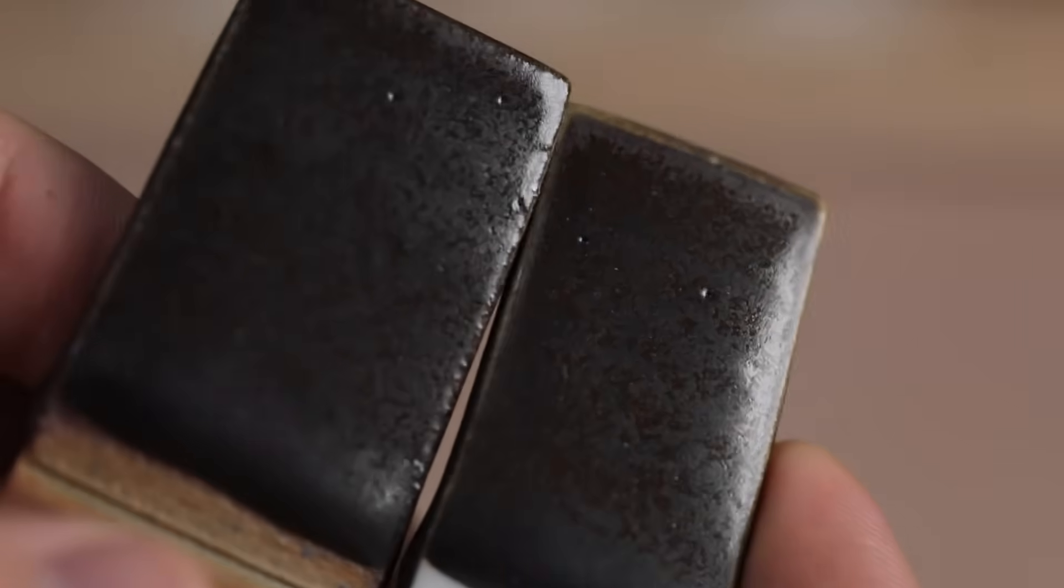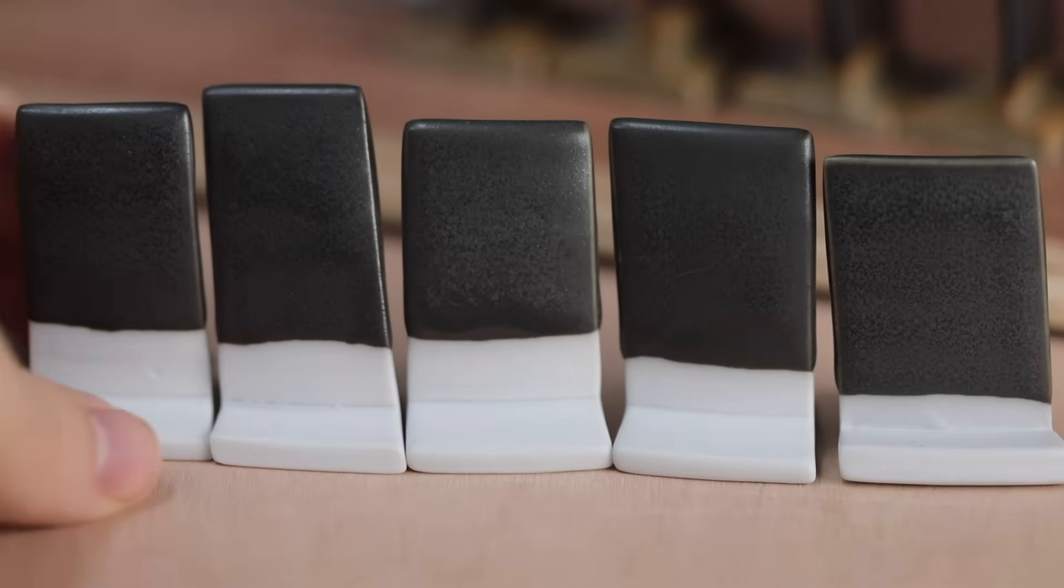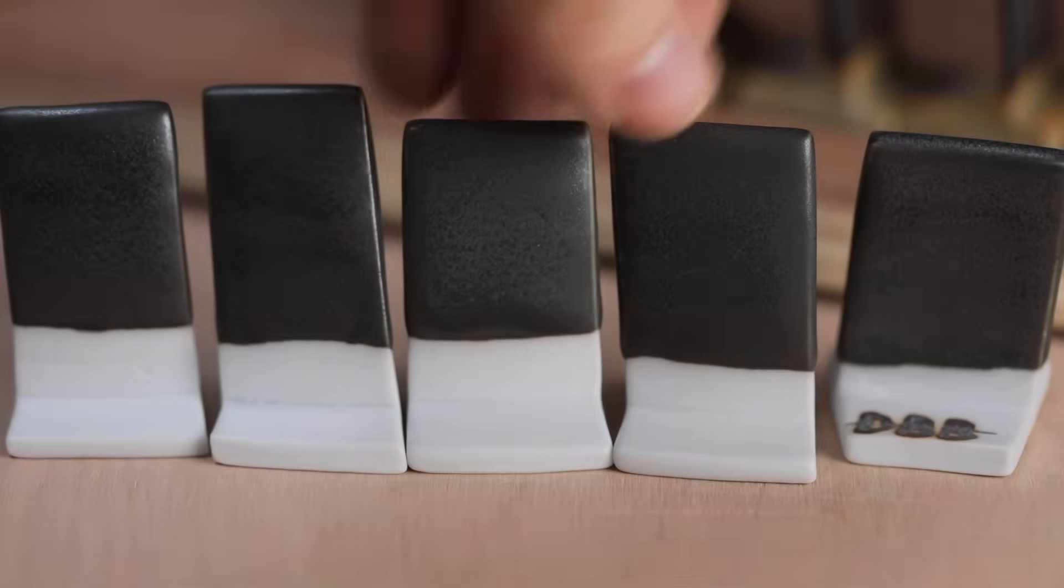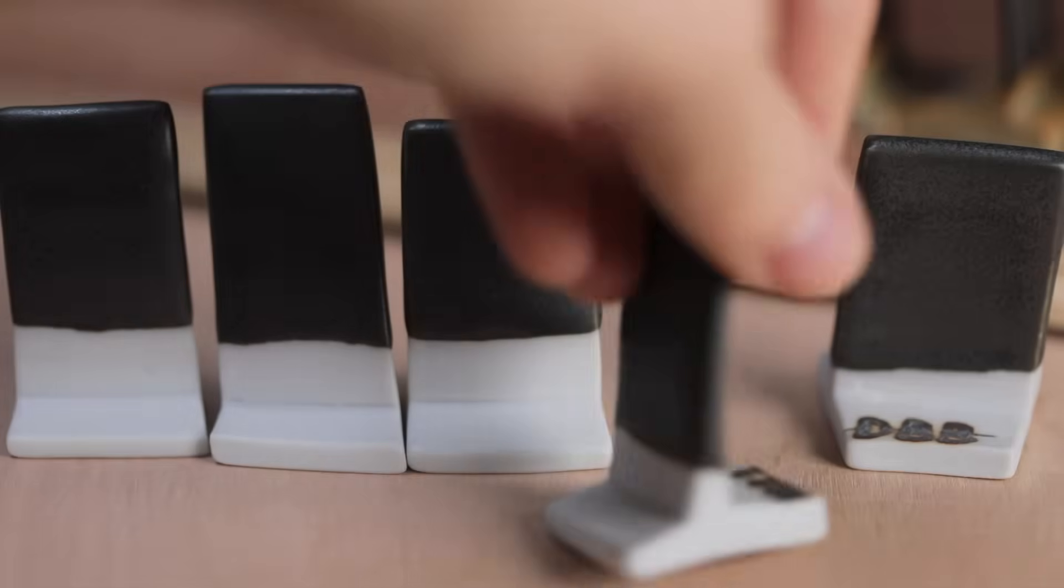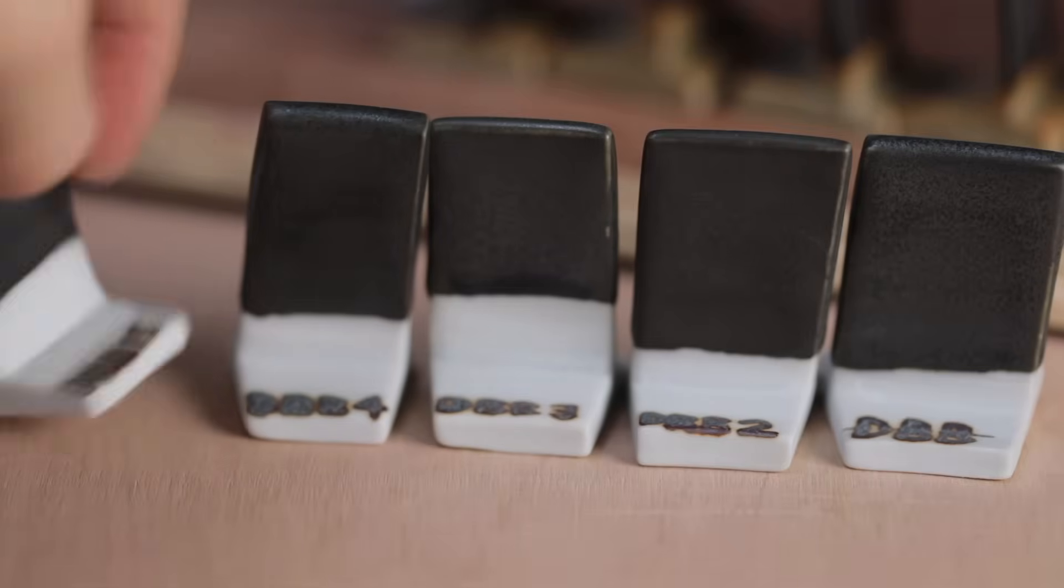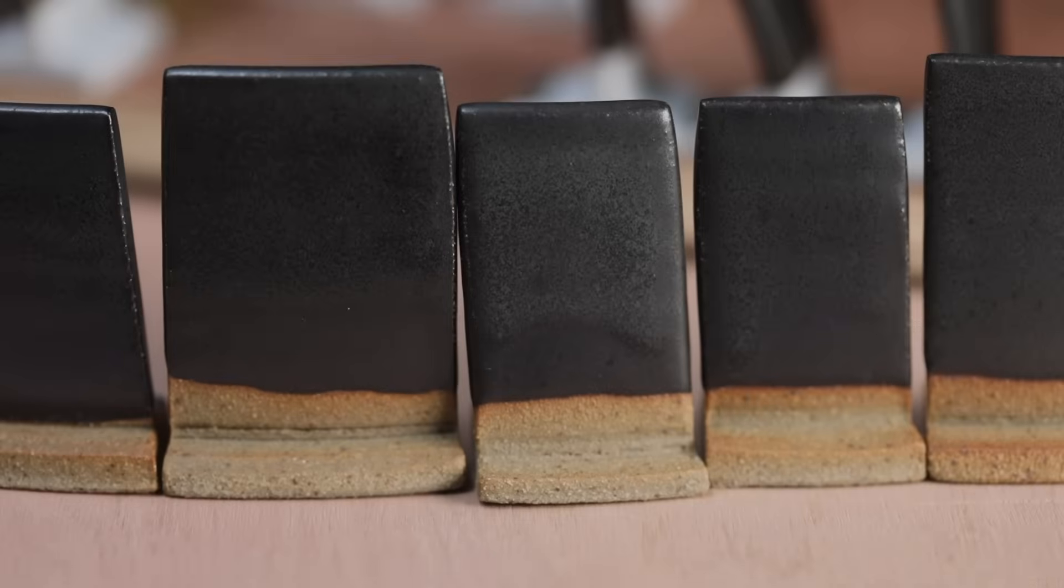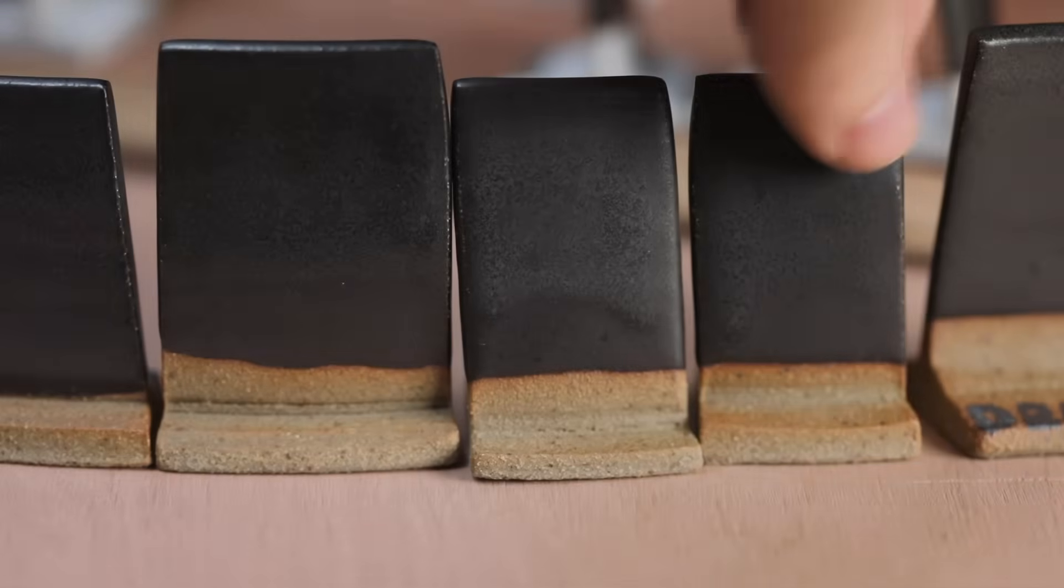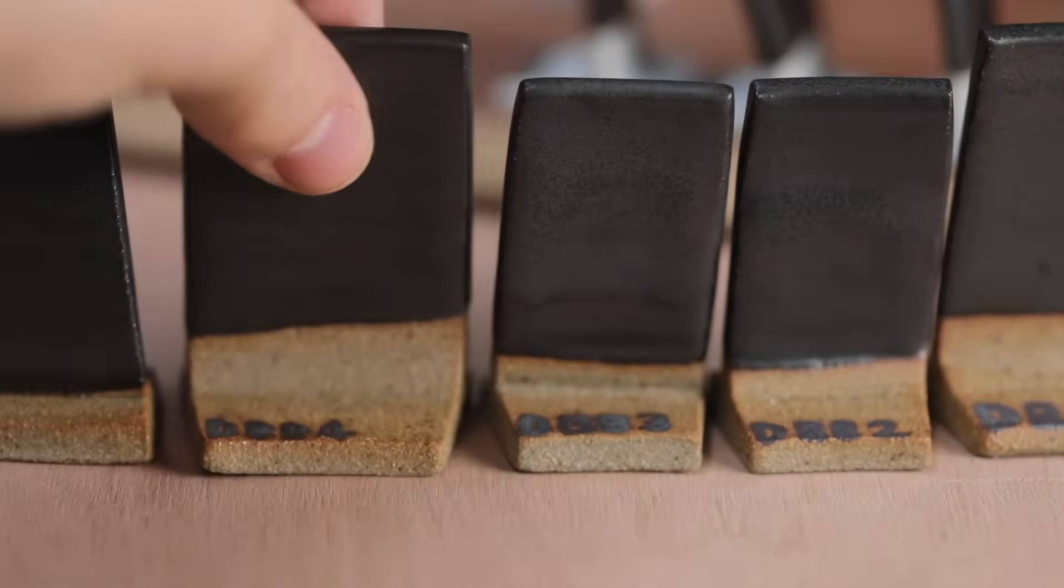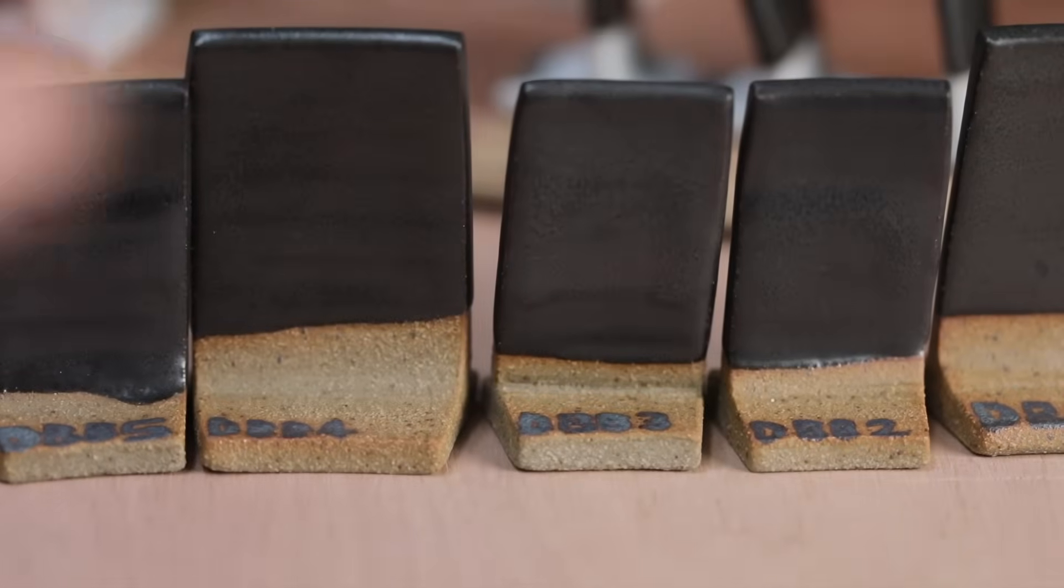And lastly, there's the blacks, which have a very simple matte surface, and pretty much from left to right here, they just contain different feldspars, different types of clay, and varying levels of black stain and titanium dioxide. This one, which contains FFF feldspar, for some reason has huge cracks running throughout it, with the glaze literally peeling off. Otherwise, they're all very similar, although number four, which I particularly like, does contain some red art clay, which is also coated on the bigger tile here, has an ever so slightly more metallic surface, and it's another glaze that feels wonderful, and matches a white that I've made particularly well, as I think you need to have a really good black and white that work well together.